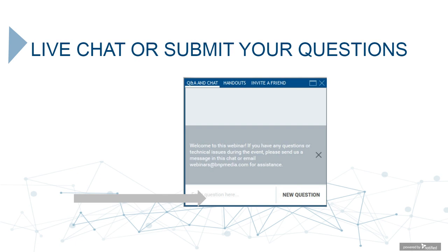Okay, the next question. Can GCMS be used to determine monomer distribution in polymers? Very good question. Yes, in principle, especially if your monomers have very separated peaks. In other words, between acrylate, vinyl, and other types of acrylate, methacrylate monomers, it's very hard. But if you are comparing, let's say, acrylate versus styrenic or acrylate versus fluorinated samples, or one which contains long alkyl chains, it's easy. So again, the further you can separate them, the better.